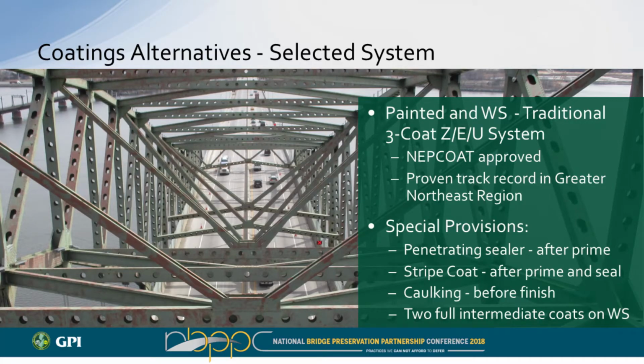And then on the weathering steel, we specified two full coats of the intermediate. And again, this goes back to the fact that the surface profile is drastically different. You've got the high highs and the low lows. You want to make sure you have that coverage. You don't want too thick of a zinc coating. That can be very detrimental to the coating system itself.